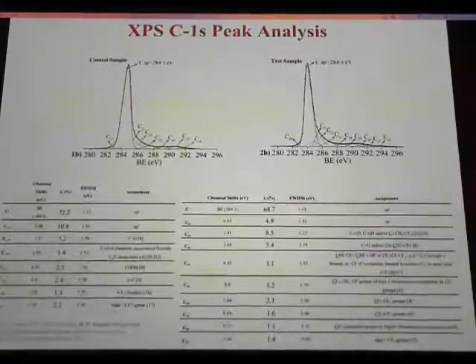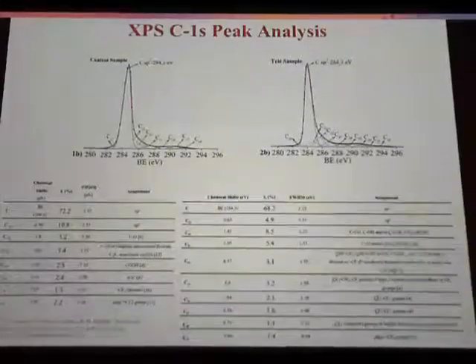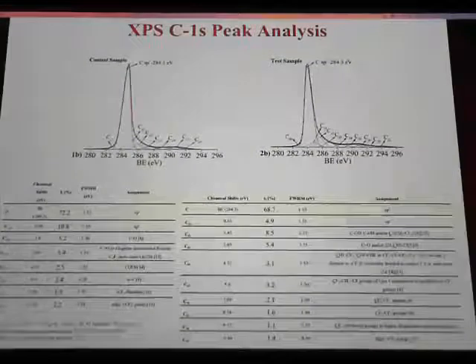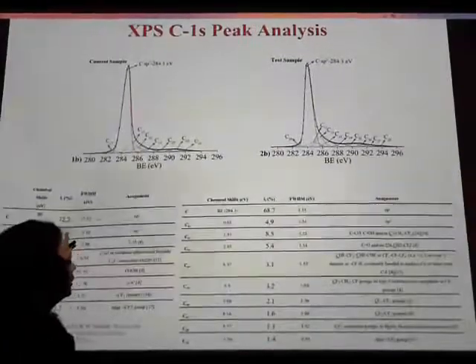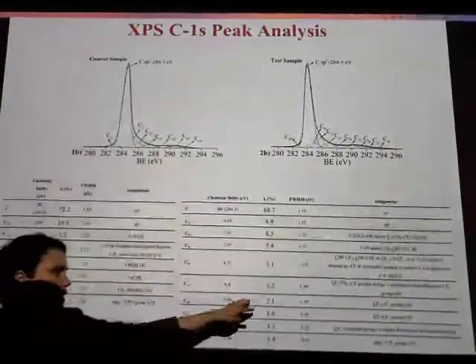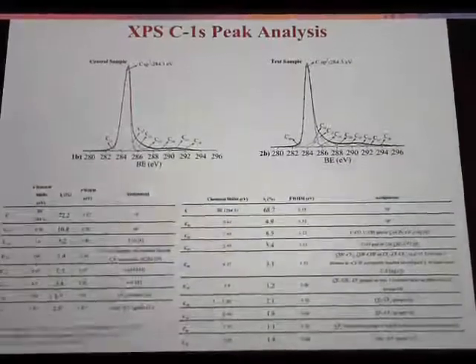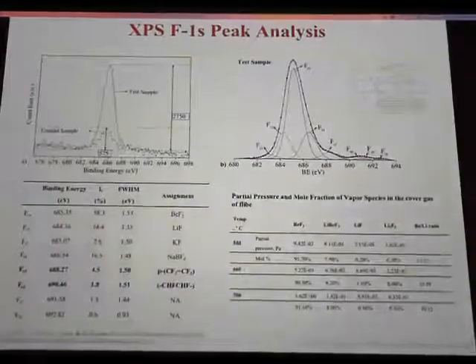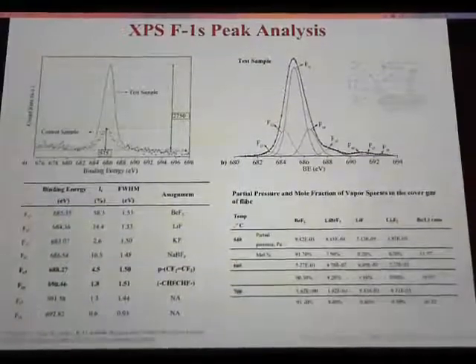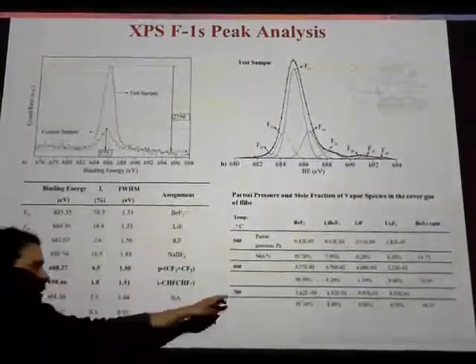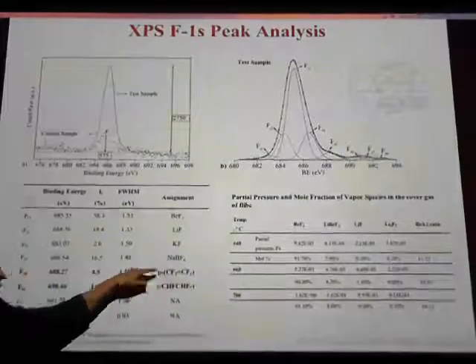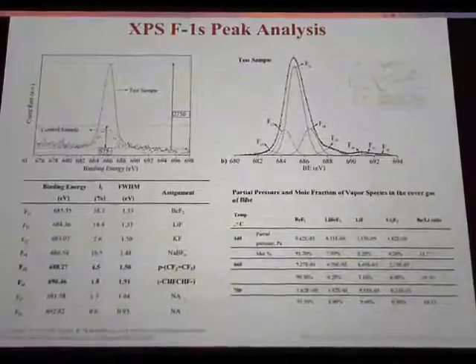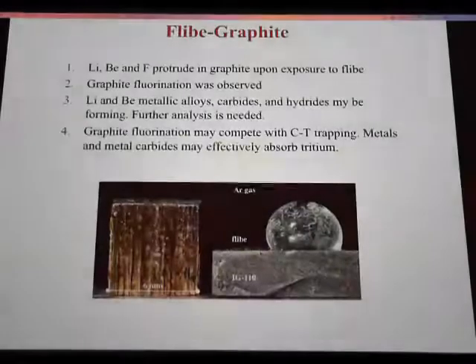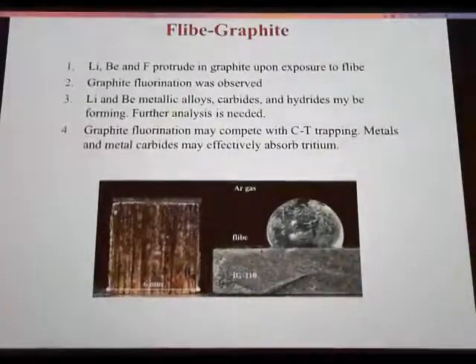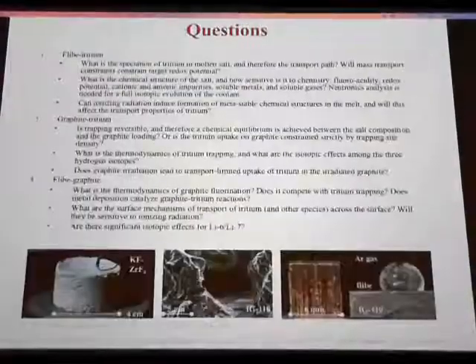Now, another thing we learned from XPS analysis of the graphite is that the graphite fluoridates. So the sp3 carbons go from 10% to 5%, and then they show up as fluorinated graphite. So we fluorinate the graphite. Not much, but a little bit. And then that's also corroborated by the F-peak on XPS, which shows the same functional forms as we saw in the carbon peak. So graphite fluorinates. Okay, so putting all of those together,